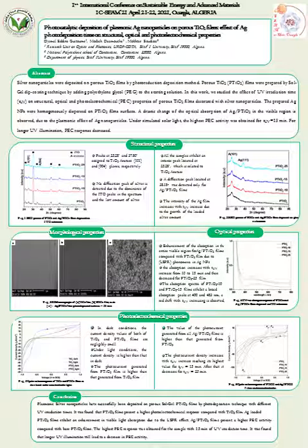Figure 1 presents XRD spectra of the prepared samples on ITO substrate. We note the presence of small peaks attributed to TiO2 anatase structure. No diffraction peak of silver was detected due to the dominance of ITO peaks and the low amount of silver.